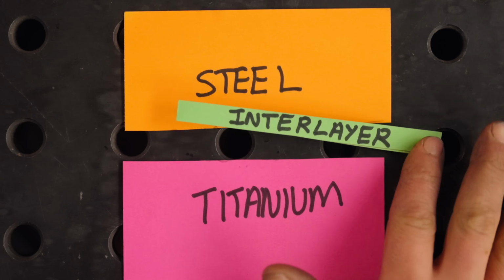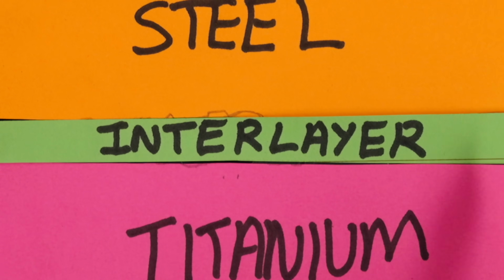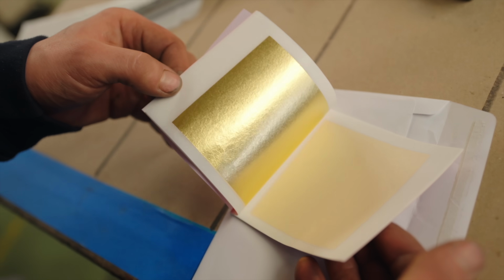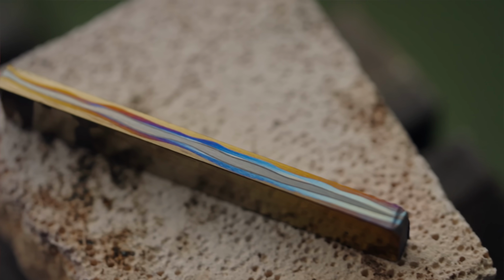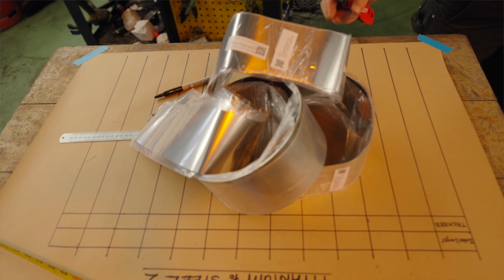My current hypothesis, based on reams of paperwork, is to work around this, we need the use of an interlayer that acts as a barrier between the steel and the titanium. In our first episode, we tested copper, nickel, silver, and gold. We got some interesting results, but we've got to go further. And so thanks to your suggestions in the comments, we have even more materials to play with.